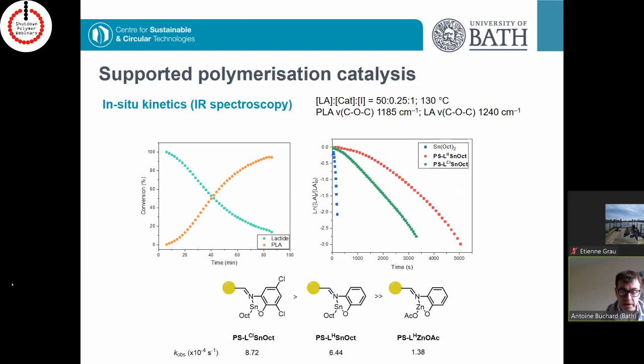We had done this initial screening at 24 hours, but we wanted to know the actual kinetics of the reaction. And to do this, what we did was to look at in situ IR spectroscopy based on the vibration of PLA here and lactide here, to try to monitor the conversion and the consumption of lactide. And from this, using the initial rate methodology, for lack of a better word, what we can see here is that clearly the gold standard of tin octanoate is so much faster than anything we can produce here.